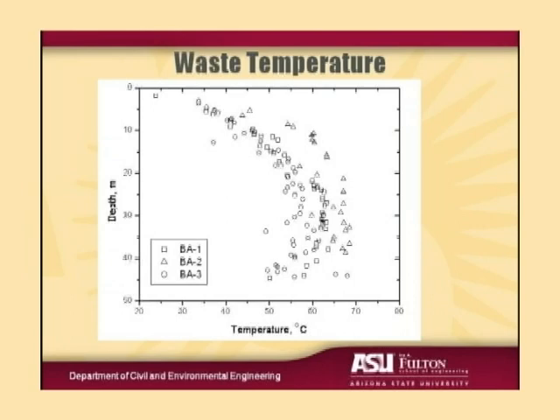If you look at this degradation plot, you'll note BA2 is down in the wet zone. That's where we had a lot of moisture, and that's where we had the highest temperatures and the greatest degradation. BA3 was at the dry end of the landfill, and that's where the temperatures were the lowest, but still elevated. You go down in the hole, and it's 60 degrees centigrade, about 150 degrees Fahrenheit. So the landfill was cooking. The waste was degrading, clearly.